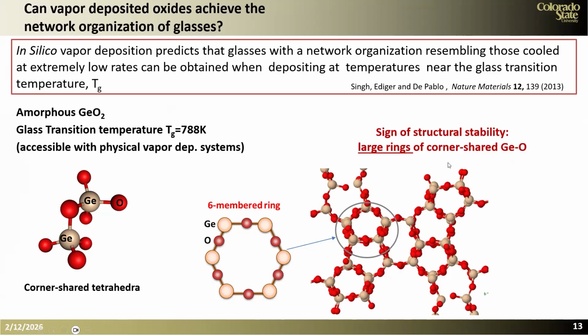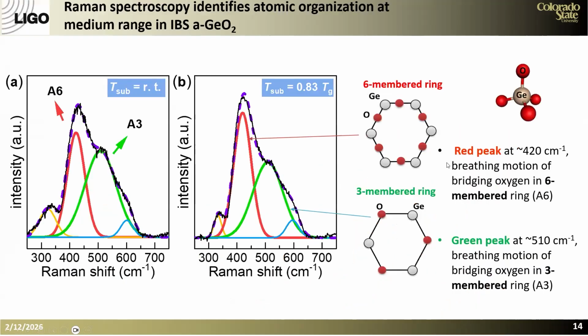And then the next thing is, in order to look for signs of structural stability, we need to be able to detect large rings. And so to do that, we conducted Raman spectroscopy measurements of amorphous germania that we deposited by ion beam sputtering using essentially room temperature for the deposition. And then also we did a separate deposition at a substrate temperature of about 0.8 the glass transition temperature.